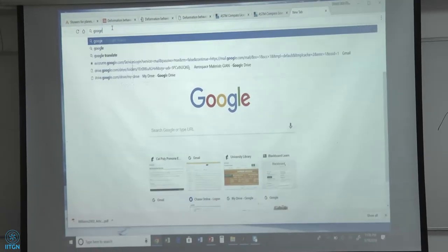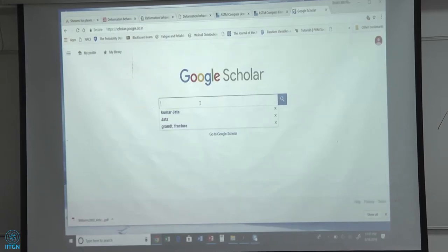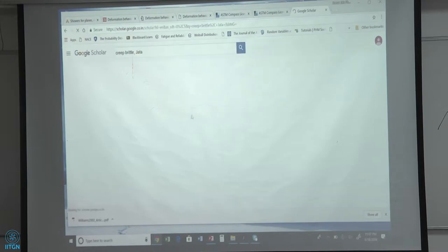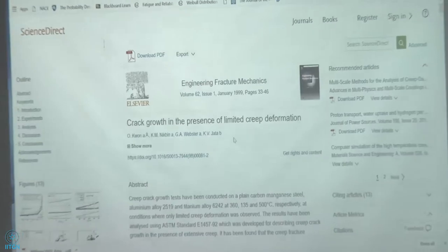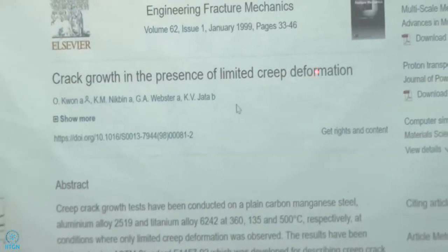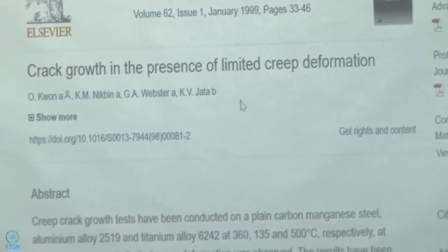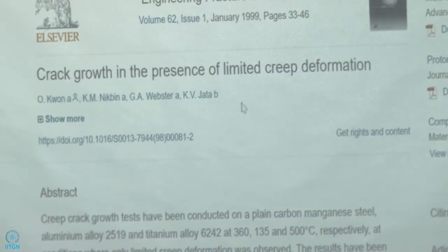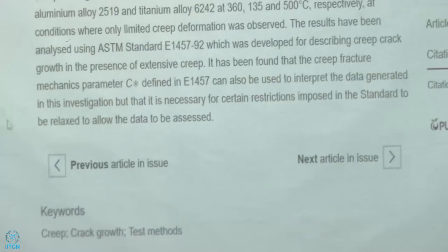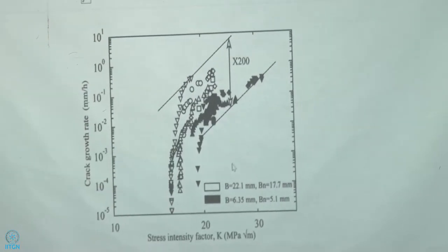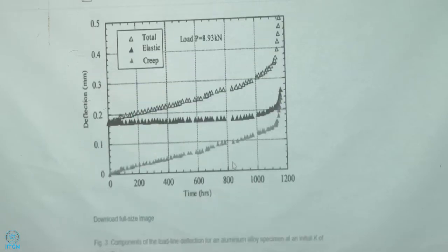The only thing I was saying was the capacitance gauge is very, very sensitive to measure these kinds of small strains. And you can also put it outside the furnace. Well, LVDT also, you can put it outside the furnace. But remember the location of the capacitance gauge. If this is your creep frame and your sample is there, the things that hold the specimen, the bar that is there, that's where you put the gauge, outside the furnace. That's my mental picture.